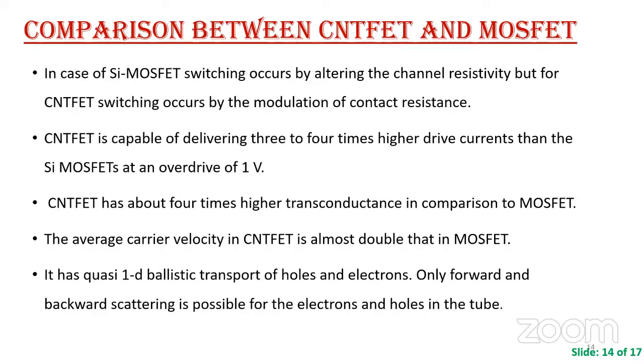There are some comparisons between CNT FET and MOSFET. In case of CNT FET, the switching occurs by modulation of contact resistance, as compared to silicon MOSFET, where switching occurs by altering the channel resistivity. CNT FET has about 4 times higher transconductance in comparison to MOSFET, and the CNT FET is capable of delivering 3 to 4 times higher drive current than the bulk MOSFET. And the average carrier velocity in CNT FET is almost double that of MOSFET.